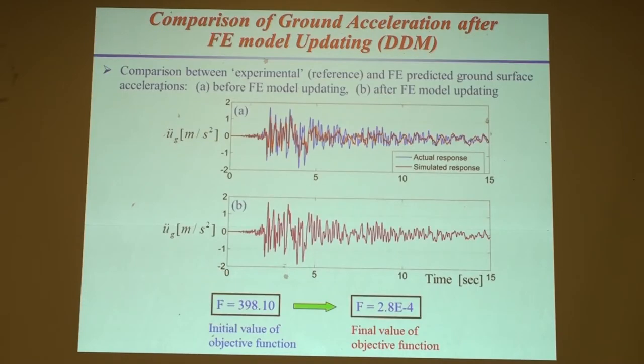And if you look graphically at what it means, the blue is the experimental result that we simulated. And then the red is the simulated response using the initial value of the parameters before finite element model updating. So you see the time history is very different. And then here, they match exactly. In this case, which is a little bit manufactured again because we don't have exact experimental data, we simulated them. You see the objective function goes from 398 to pretty much zero.